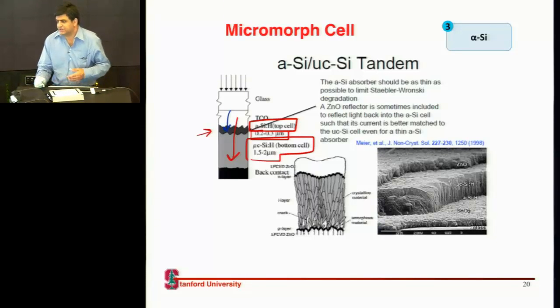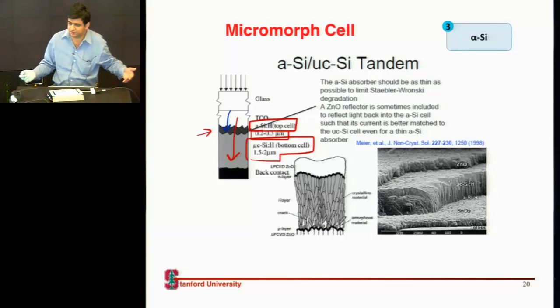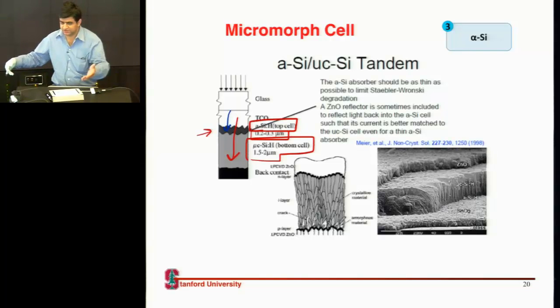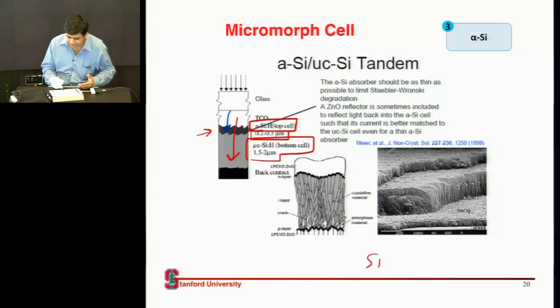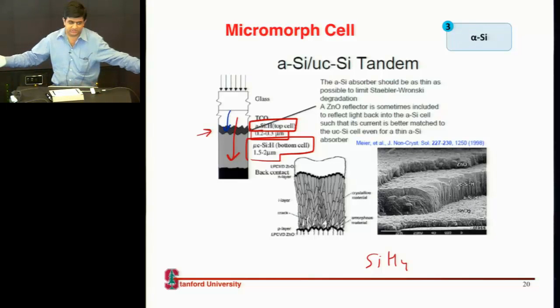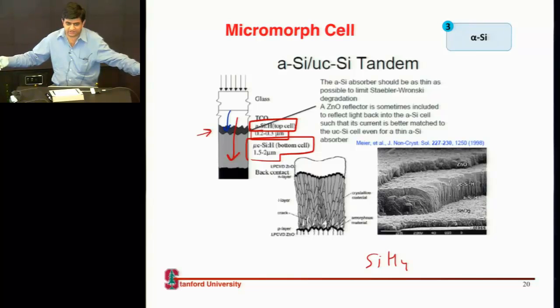The other thing about this amorphous silicon or microcrystalline silicon is that you have to deposit it in a high vacuum, or you have to do the CVD of these things in a relatively high vacuum process. So it's not that you can make an ink of amorphous silicon and spray it and make this material. You have to design these chambers where this material would come in, and the silicon is typically deposited by cracking of this gas silane. So it would take you 30-40 minutes to deposit this couple of micron of silicon on one panel.